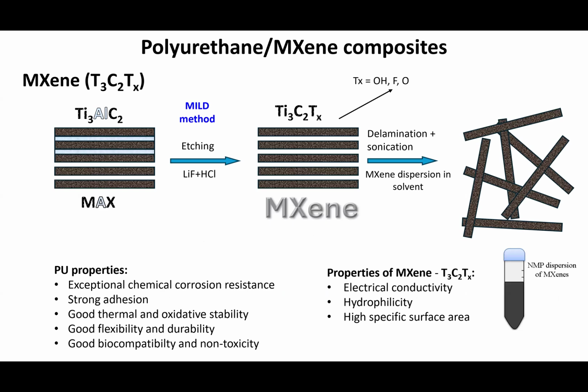Okay, so I will just switch gears. I will discuss a little bit MXenes. This is our even more recent work. MXenes are a class of materials which are highly tunable because you can functionalize them. And we produce ours using the mild method, which involves etching, delamination, and sonication, and then dispersion in solvent. And then from the solvent, you can deposit these MXenes on your polymer substrate.